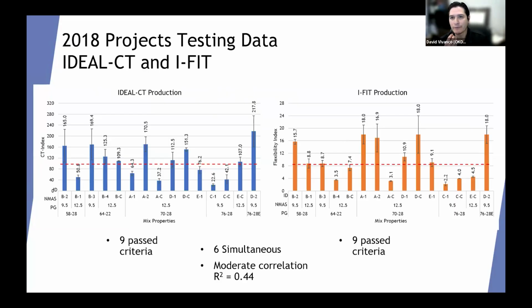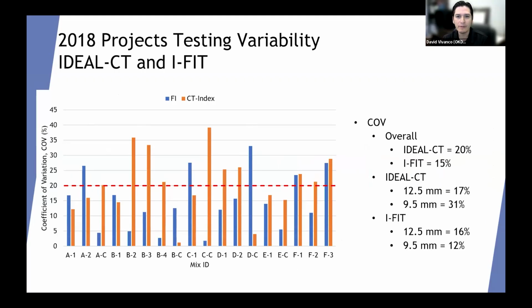In terms of the cracking test that we look into, at first in 2018, we looked into IDEAL-CT and I-FIT, and tried to see which one we were going to move forward with. In that case, we did 8 projects, a few mixes, control, and BMDs. On both tests, 9 out of those mixes passed criteria, but 6 of them passed on both tests. We showed a moderate correlation of 0.44. And we also analyzed variability in those tests. IDEAL-CT showed an overall variability of 20%, and I-FIT lower, 15%. We typically try to keep that variability around the 20% mark.